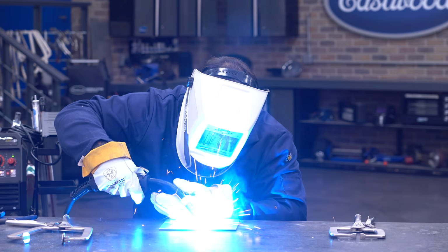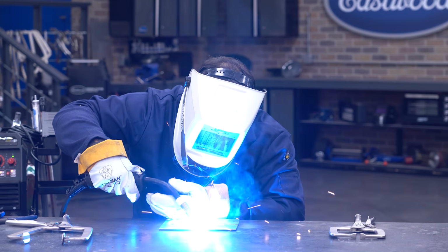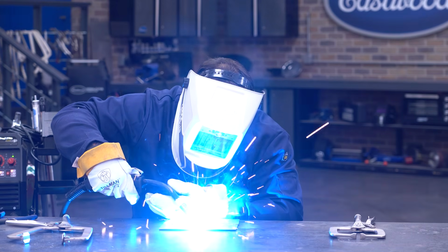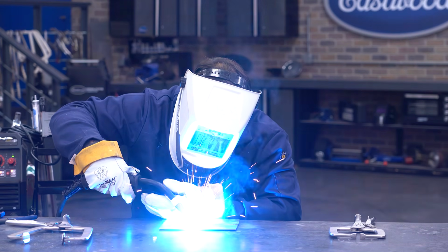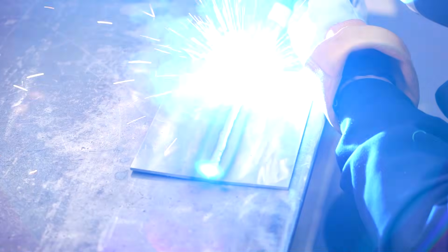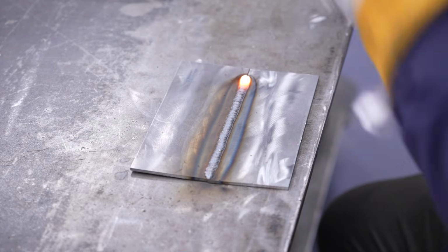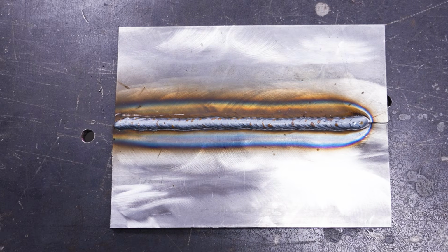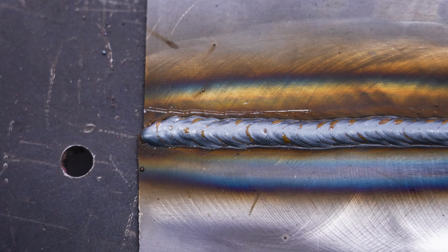So as you guys can see, my stick out is remaining consistent. I'm 50% on each plate on both sides of the weld seam, and each of my beads are running about a 50% overlap on the previous bead. I'm not traveling too fast or too slow. Kind of reading the puddle and moving when it tells me it's ready. And there you have a nice clean butt weld, tack to tack.